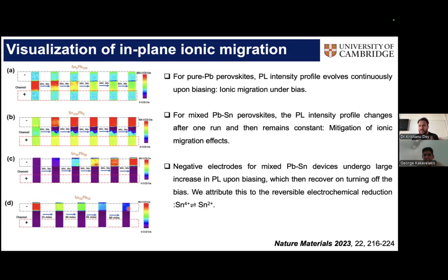So something seems to be happening when you are applying the bias, and this is where we propose a reversible electrochemical reaction where the tin 4 plus, which I said is almost certainly present in these materials, gets reduced to tin 2 plus in the presence of these electrons. And this tin 4 plus is known to be a big source of defects. So as you are reducing the defects in situ by these negative electrons, you are getting a higher and higher PL.